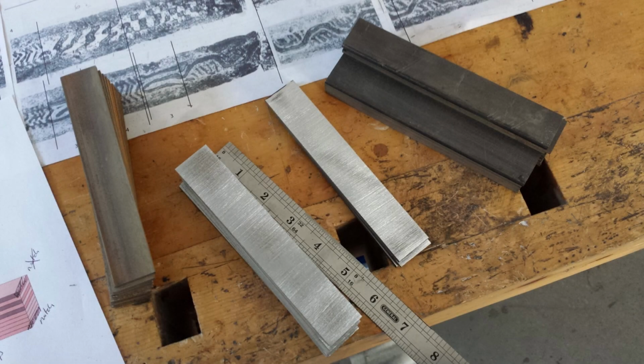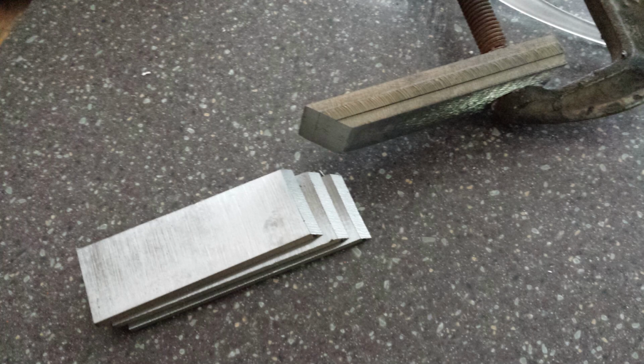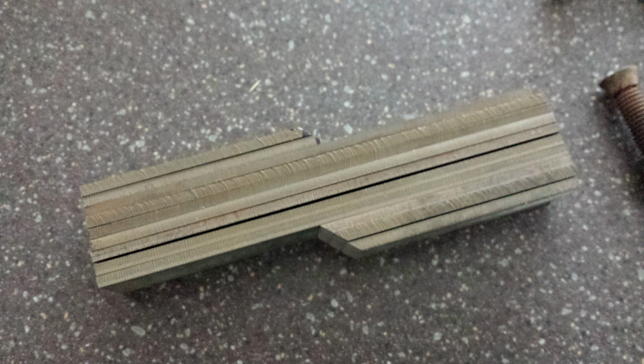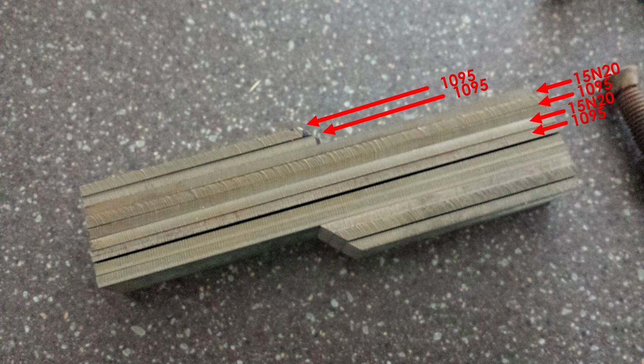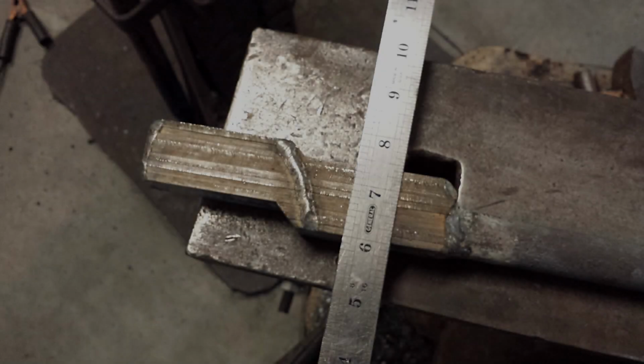Let's get started. I will begin by gathering and preparing some steel bars. I will use 6 by 1 inch steel bars of 1095 and 15N20. All the bars were 1/8 of an inch thick. 3 of the 1095 bars are cut at 45-degree angles through the center. The billet is built starting from the top using 2 half layers of 1095, followed by full layers of 15N20 alternating with 1095 3 times. Add 1 more full layer of 1095 and finish with 3 half layers of 1095, and we are ready to forge weld.